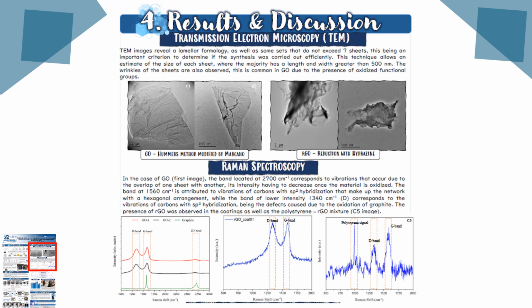Finally, in the spectrum of the right, with a lot of noise, we can see the RGO bands and a very characteristic peak of polystyrene. This shows the mixing of both materials, the interaction between them, and π-π stacking interaction, as both have aromatic rings in their structure that interact with each other without damaging their individual structures.